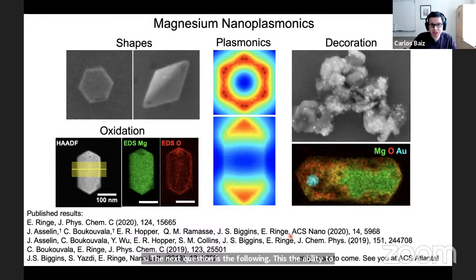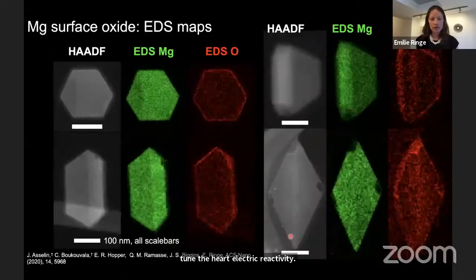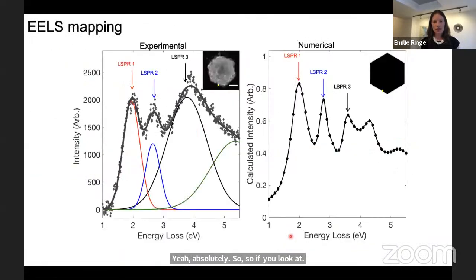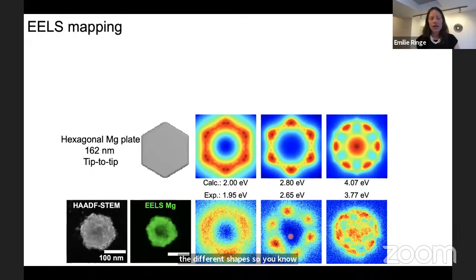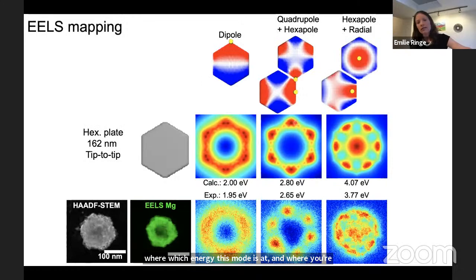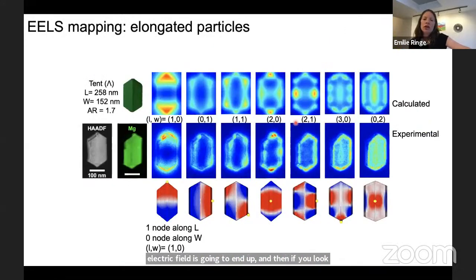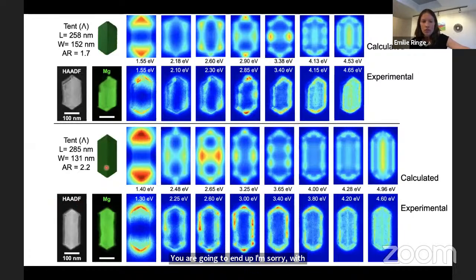Does the ability to access different shapes in magnesium allow for easier localization of the LSPR modes in different parts of the nanoparticles and to tune the hot electron reactivity? Yeah, absolutely. So if you look at one shape, you can have different types of modes at different energy. Now you can tune which energy this mode is at and where your electric field is going to end up. And then if you look at different shapes, you are going to end up with different mode localization, again at different energy. And that is true of the more pointy shapes like the kites and so on.